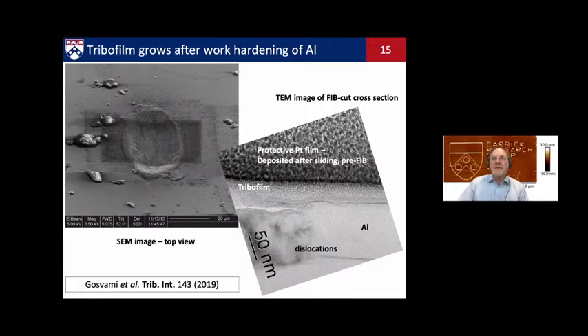So there can be tribofilm growth on aluminum. You just have to get the stresses high enough, which means getting the aluminum hard enough. So we think stress is the key. Now there will be chemical effects. The bonding of this tribofilm to the aluminum may well be different. It may be probably weaker than on steel. Likewise, steel may also have catalytic effects. So the actual composition of this film may be rather different than what you get on a steel surface.